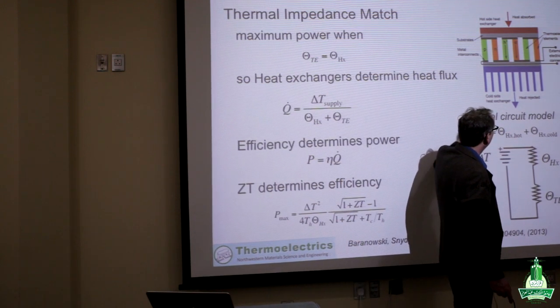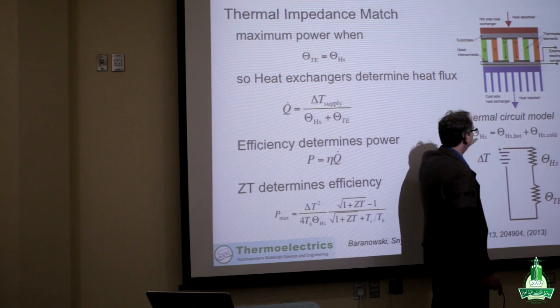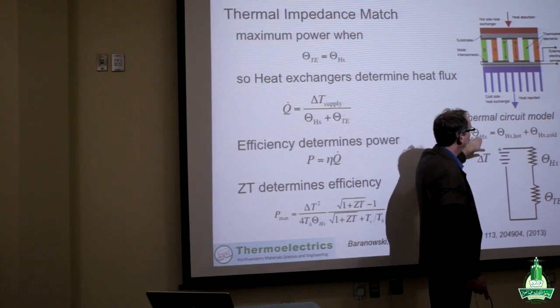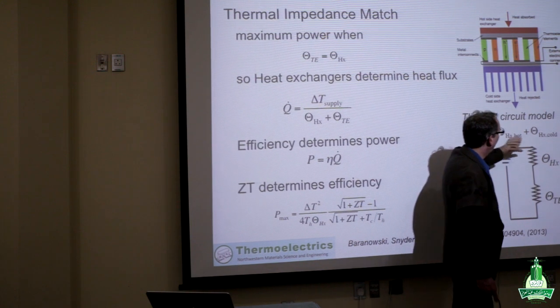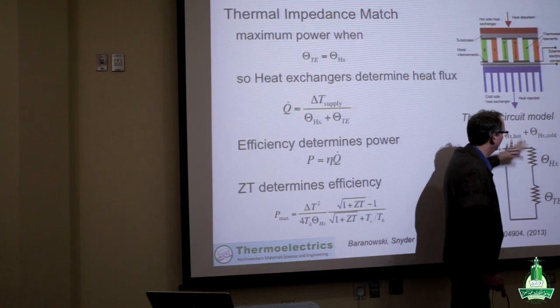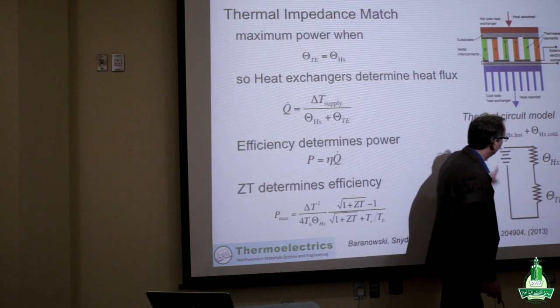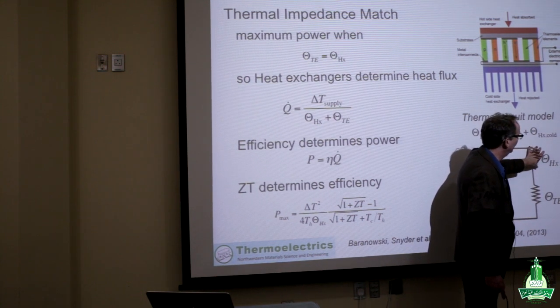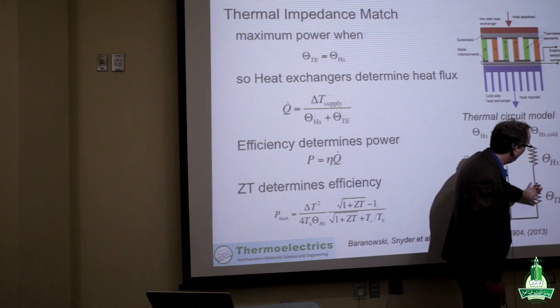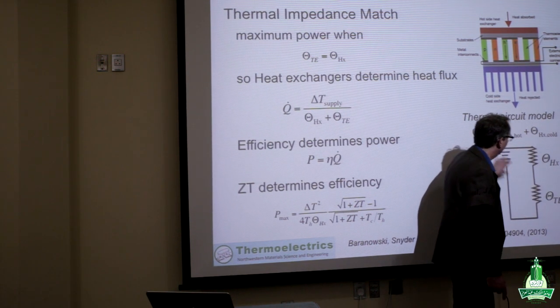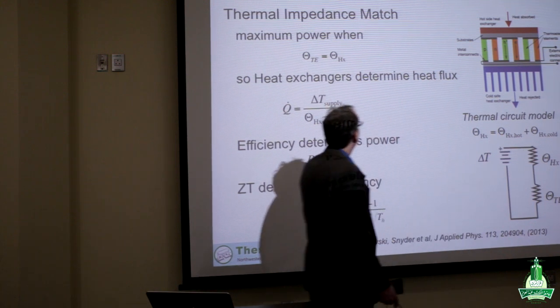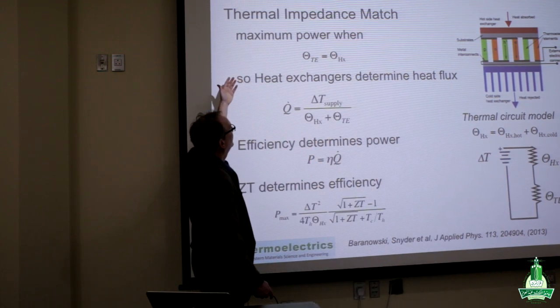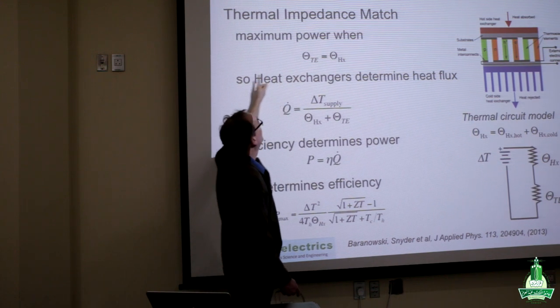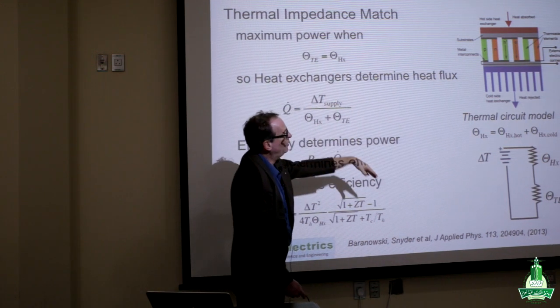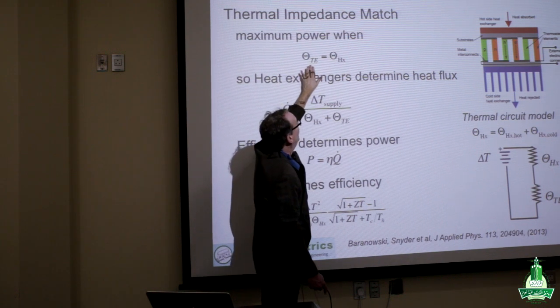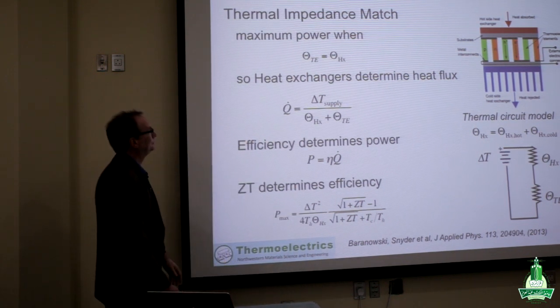We'll make a thermal circuit model where we find an effective thermal heat exchange impedance, which is approximately the sum of our hot side and our cold side together, and draw a simple circuit again where we have the lumped sum thermal impedance and the thermoelectric thermal impedance in series. And once we do that, we come up with the same condition that we had for electrical, which is that for maximum power, heat power through our system, we should have thermal impedance match as well.